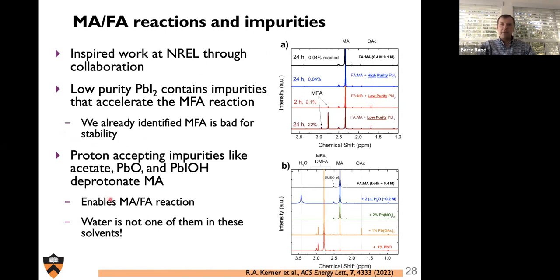And here are those data, whereby if you have FA, MA, here's the NMR data that shows no byproduct in this situation. This is DMSO free. And even in the case where you load that system with high purity lead iodide, we don't have the presence of MFA. However, if I introduce low purity lead iodide, we see these peaks in the NMR that can be assigned to MFA.